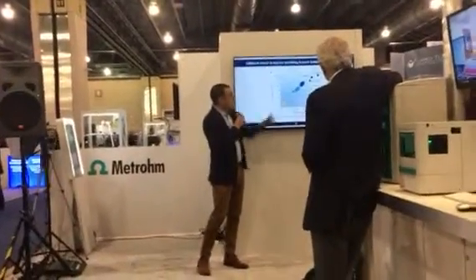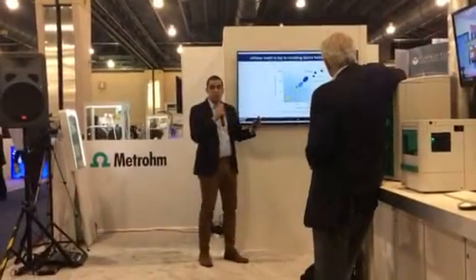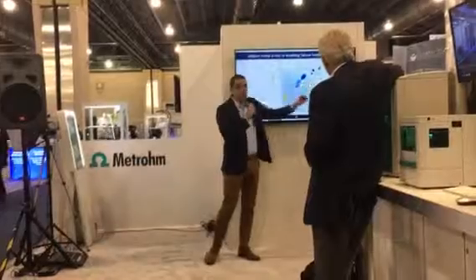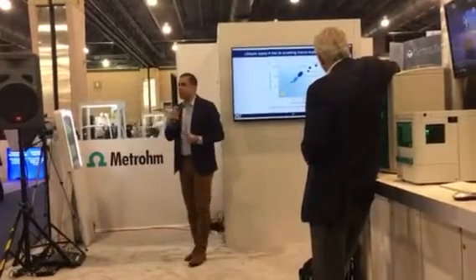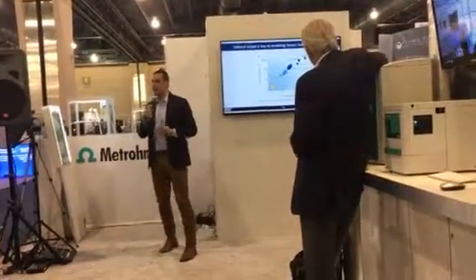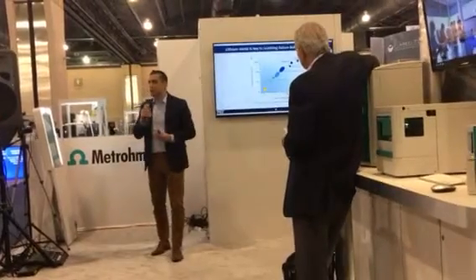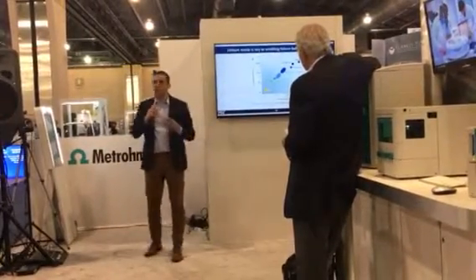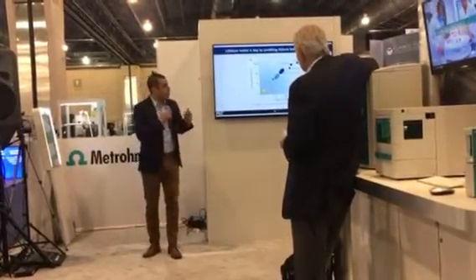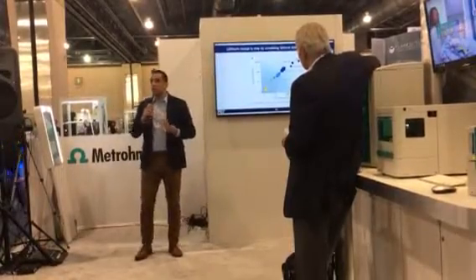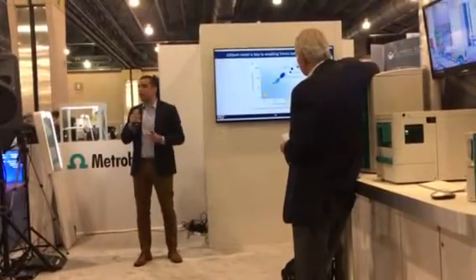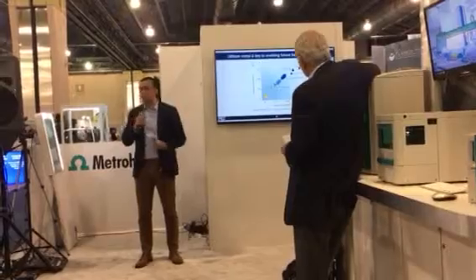You need to go up on this graph here. And to do that, the key is really this lithium metal anode. So lithium is really the basis for all of these technologies. Right now we store it combined with some other materials. So we can store it with some metal oxides or some graphite. But when you have pure lithium metal, it can actually store about 10 times the capacity of these conventional materials that are in our pockets today.